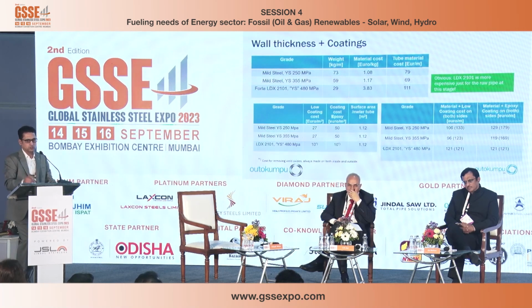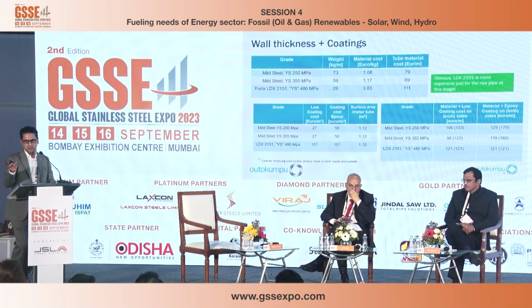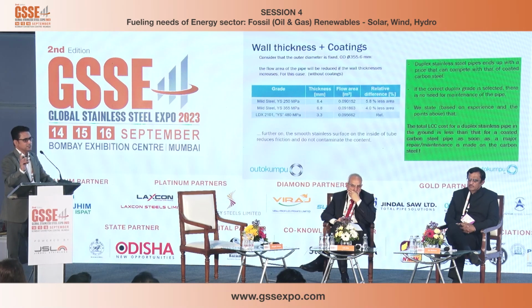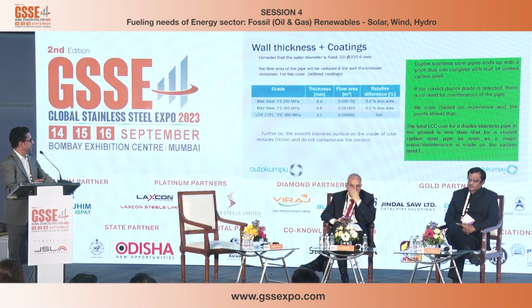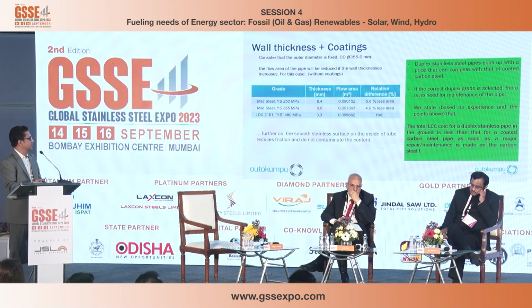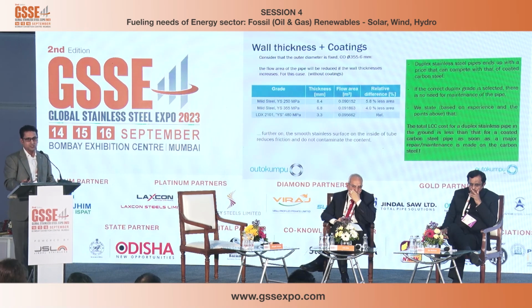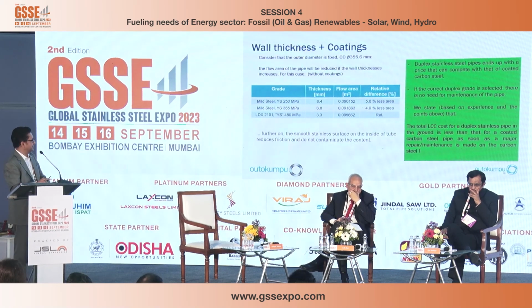I'm not talking about the service life or maintenance or something. So wall thickness plus coating, again not talking about the maintenance cost. When you use the lower thickness, you have more flow area available when you are using duplex, so you can push more material into that, more liquids, and increase your capacity. So duplex stainless steel pipes end up with a price that competes with the coated carbon steel.